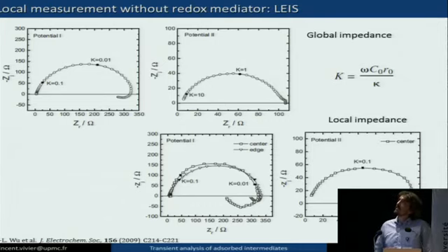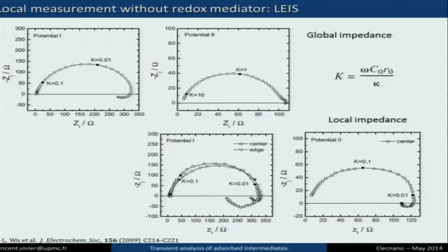We did the same thing as before for the iron. So we investigate 2 different potentials. At a small overpotential, we have an inductive loop, a capacitive loop, and an inductive loop. Whereas for larger overpotential, we have a capacitive loop and another small capacitive loop. Now the frequency on this plot refers to this dimensionless frequency here, with the pulsation, the double layer capacitance, the electrode size, and the electrolyte conductivity.